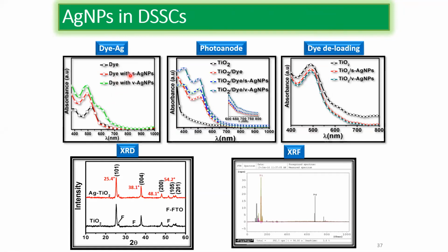Here we can see the UV-visible spectrum of my dye all alone, N719 dye. When I mix it with a spherical nanoparticle, Ag NP, we see that absorption is not improved much, though some good improvement is there. But when we mix with the mixed-shape nanoparticles, we observe a broad increment in absorption. So my nanoparticle works very well with the dye molecule; it has some coupling with it. I then tested with a photoanode in a thin film, and absorption increased very drastically when I applied this material in the TiO2 and dye photoanode.